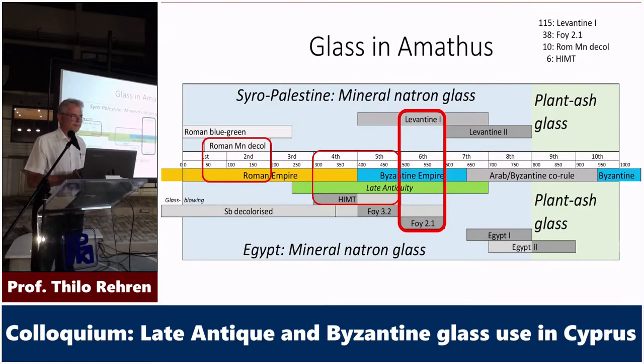So we can plot that back into our graph of timeline here. And the majority, 115 here, are Levantine glass. The next biggest group, 38, are Foy 2.1 from Egypt, most likely. Nicely in the 6th century, which I'm pleased to say matches what the archaeologists already knew before me. But it's good to have independent indication for it as well. The HIMT glass is a little bit earlier, 4th into the 5th century. Not a surprise that that is very little here.